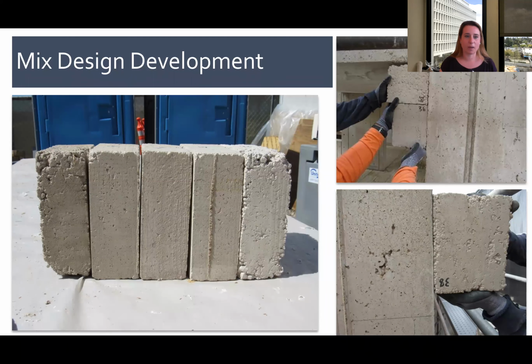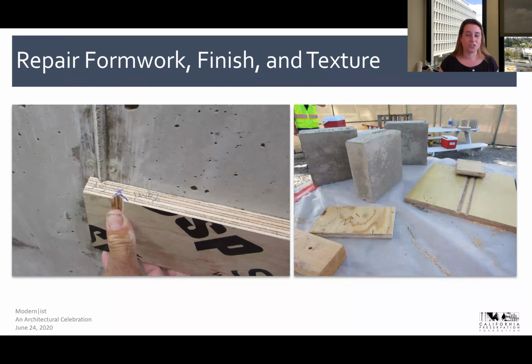Once we had this palette of 5 colors, we were able to compare them and they pretty much matched everywhere within the building. And again, just as the formwork was critical to the success of the original construction, formwork was going to be critical to achieving repairs that matched, both in getting those details with the fins and the form tie holes, but also the surface. We had to get the right kind of surface.